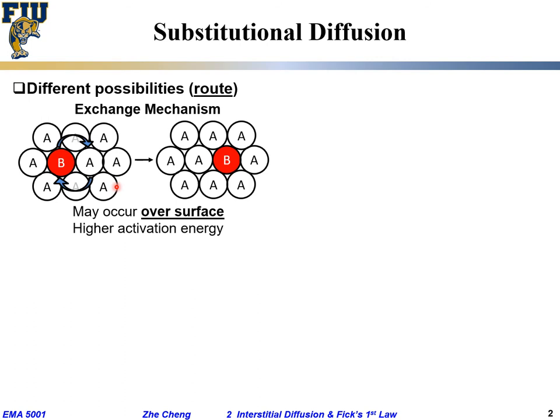So typically this mechanism or route, remember we said mechanism means route, doesn't really happen within the bulk. It may happen, read to yourself, over the surface, because at least that's one free region on the top where things can exchange. It needs high activation energy. Okay, so that's the so-called exchange mechanism for so-called substitutional diffusion.